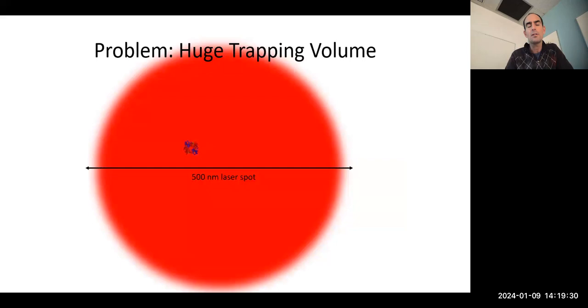Another issue with using a typical diffraction-limited spot is that it's huge. You can focus light down to about half a wavelength in a good microscope, but if your wavelength is in the infrared, around 1 micron, that's 500 nanometers. If you're interested in looking at nanoparticles — I've shown hemoglobin here, a tetramer protein, but any quantum dot or lanthanide-emitting nanocrystal is a similar size, tens of nanometers across — you're going to have a challenge isolating just one.